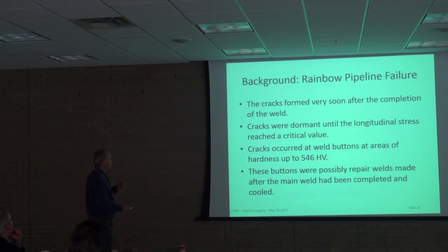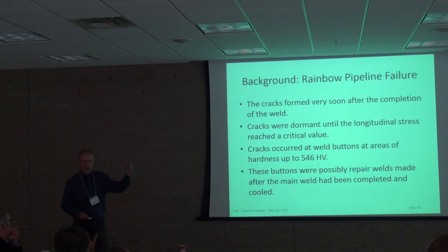So the interesting thing about these cracks is that they were there right away. Just like I explained, one of the standard things in welding inspection now, if you're doing MPI, looking for these kinds of cracks, the rule of thumb is you do it 48 hours after the weld has been completed and cooled. Because it takes time, a lot of times, for these cracks to appear, so you can miss them. If you weld it up and then do your inspection and then leave it, 8-10 hours later it's cracked.